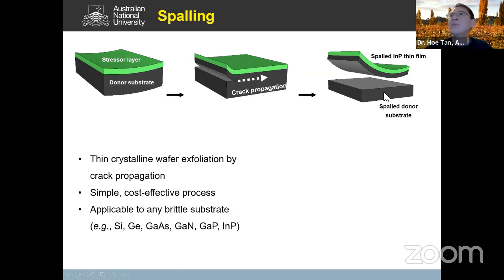And in fact, you can do this multiple times. Okay? Once you've done this, you can deposit another stressor layer on top of this so you can reuse the substrate. Okay, and in fact, we've demonstrated we can do this about 10 times before the material quality drops. So this is a simple and cost-effective process, and it is applicable to all sorts of brittle material, but more importantly, it must be a crystalline material. Otherwise, we cannot control the crack propagation.